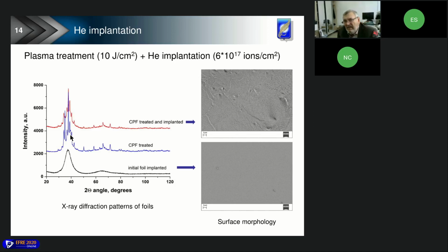Surface morphology investigation after plasma treatment and helium implantation again shows just developed roughness and waviness that did not differ from the surface morphology before implantation. Following annealing and microscopy investigations do not give adequate information on blister formation of the sample treated both by plasma and implanted by helium ions. Just due to developed roughness of the samples after plasma treatment, we do not see blisters here. So we cannot now answer the question whether the crystallized structure of the foil possesses worsened resistance to blistering or not. In any case, we are working in this direction.